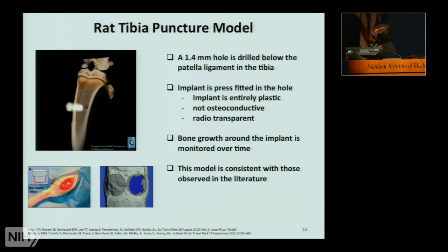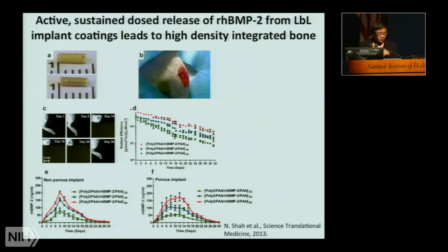We create a defect in the rat tibia. We take either a plastic or a titanium implant, coated or uncoated, insert it in, and then over time, we are going to observe the bone material interface using several metrics, including histology, mechanical properties, and just general measurement of the concentration of growth factor and other factors in the area.